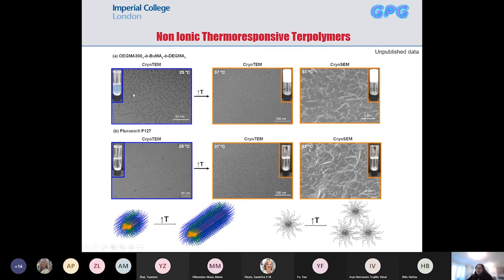And we did see this. I hope you can see it in the cryo-TEM. It wasn't easy to observe this at 37 as well with the cryo-TEM, but thankfully with the help of the University of Warwick, we've managed to achieve that. So we do have some worm-like structures from the room temperature, and this is still there and even more evident in the cryo-TEM. I hope the resolution is good enough.